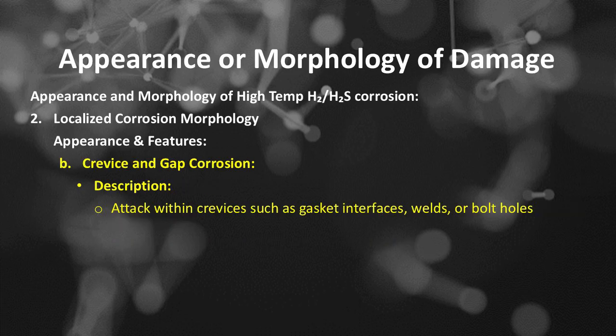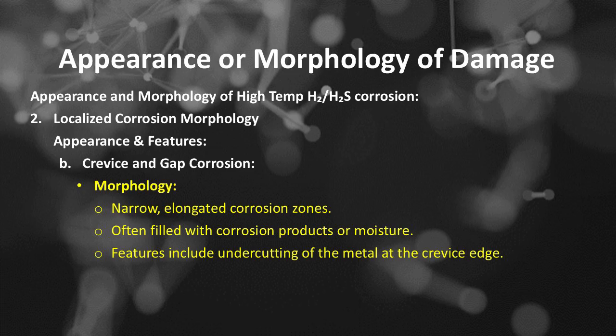The number B of the appearance and features of localized corrosion is crevice and gap corrosion. The appearance could occur when attack within crevices such as gasket interfaces, welds, or bolt holes. The morphology of crevice and gap corrosion: narrow, elongated corrosion zones, often filled with corrosion products or moisture. Features include undercutting of the metal at the crevice edge.